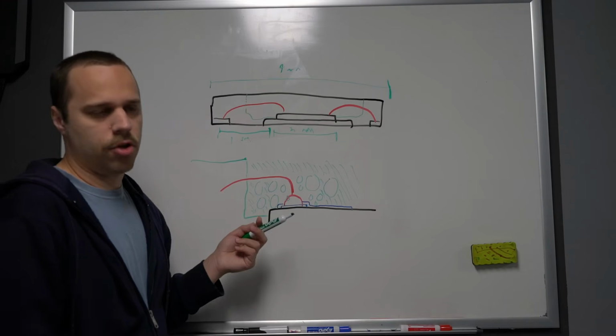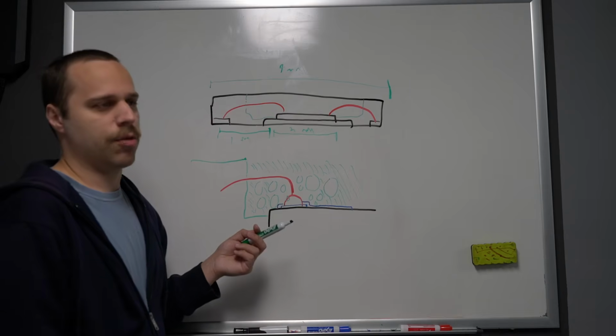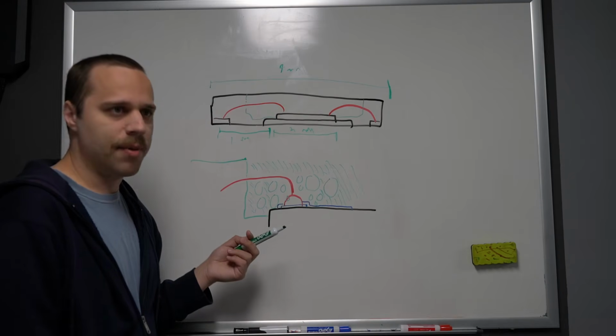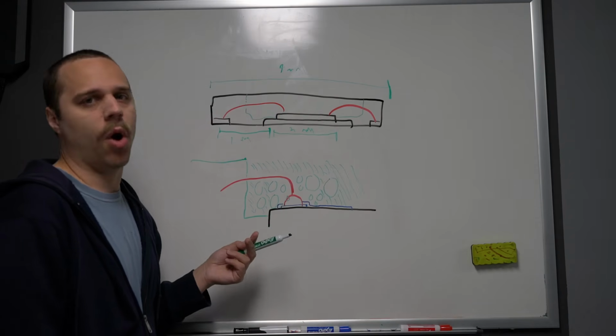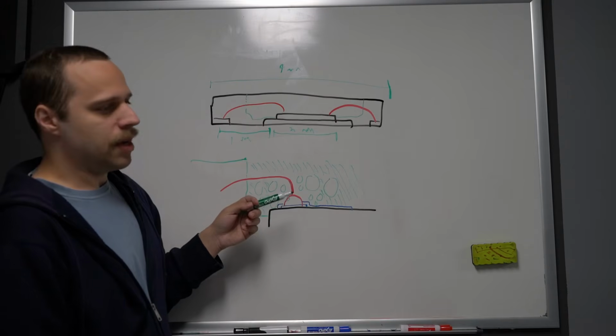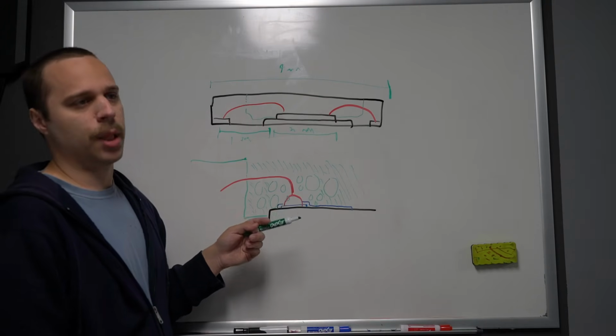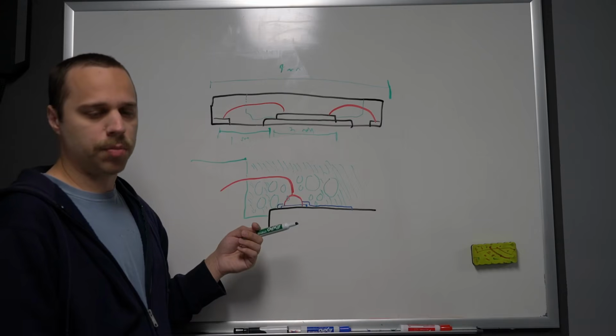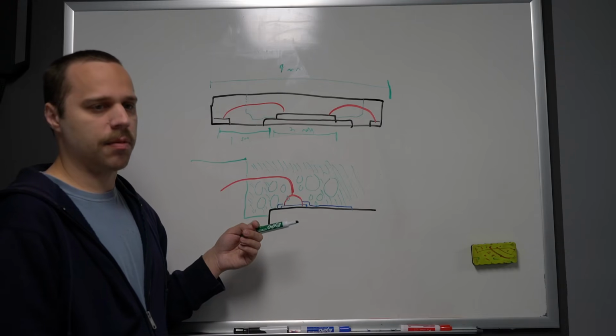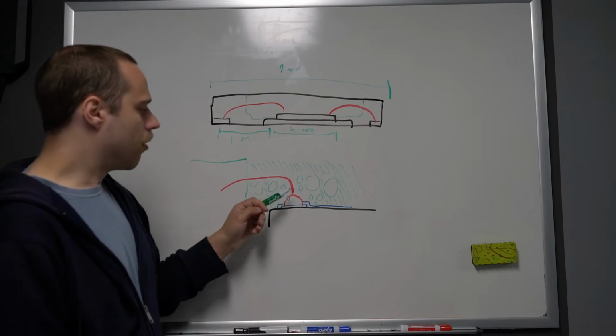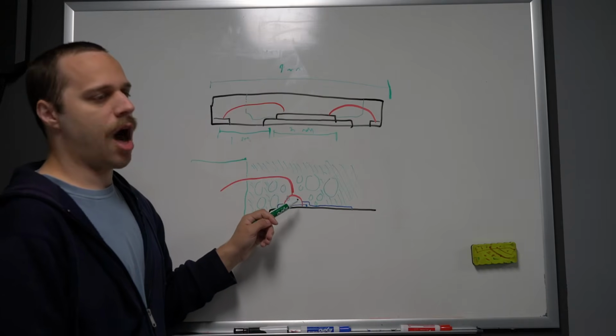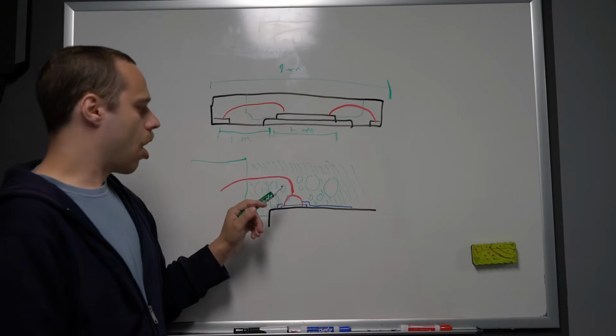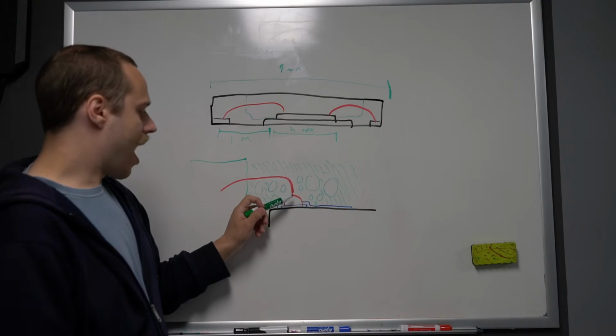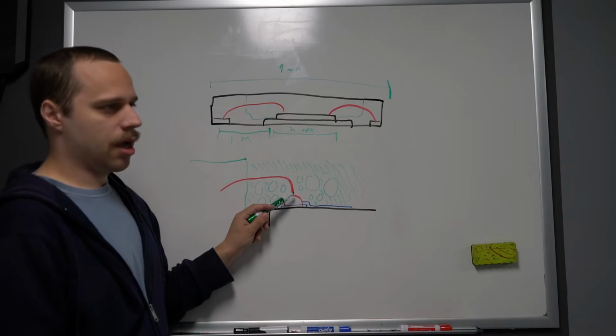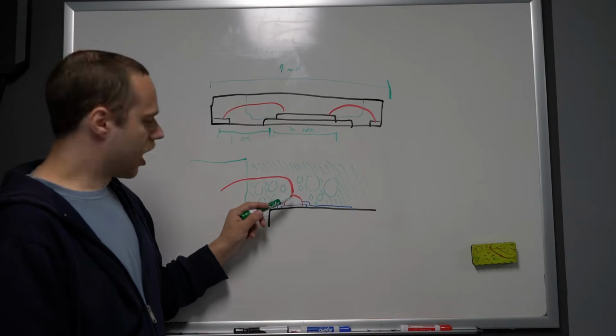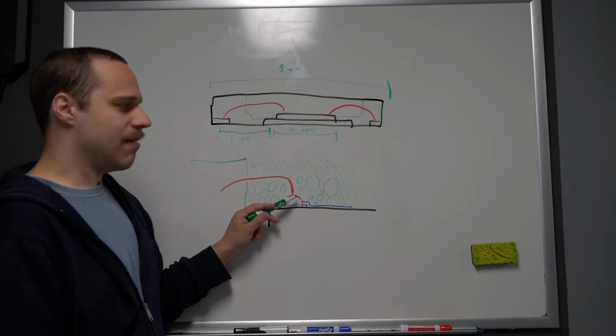Unfortunately, I don't have access to fuming nitric acid. It's both very expensive and also quite unstable, and in a personal lab, I don't really want to keep it around. On the other hand, 70% is significantly more stable. It's much easier to get hold of from general chemical suppliers. It's not like a specialty exotic material. Unfortunately, 70% nitric will eat copper immediately. So the best results that I've had are actually by mixing concentrated sulfuric with the nitric, and the sulfuric acid behaves as a dehydrating agent.